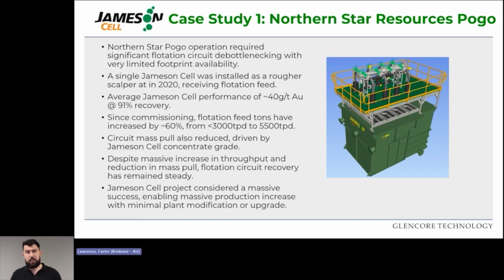Since commissioning, the flotation feed tons have increased by 60%, from below 3,000 tons per day to above 5,500 tons per day. The circuit mass pull has also been reduced, which is driven by the high Jameson cell concentrate grade, which is from the wash water system on the Jameson cell. And despite this increase in throughput and reduction in mass pull, the circuit recovery has remained steady. So at Northern Star Pogo, the Jameson Cell project has been considered a massive success, and it has enabled that massive production increase with minimal plant modifications.